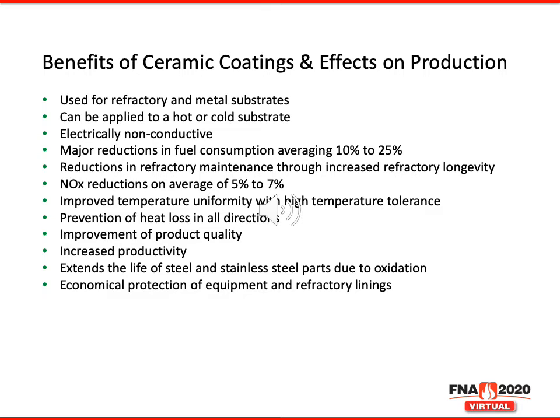There are major reductions in fuel consumption, averaging 10 to 25%. Refractory longevity can be increased by 2 to 3 times its uncoated life, thus reducing the high costs of refractory maintenance. On average, NOx is reduced by 5 to 7%. Temperature uniformities are greatly improved.